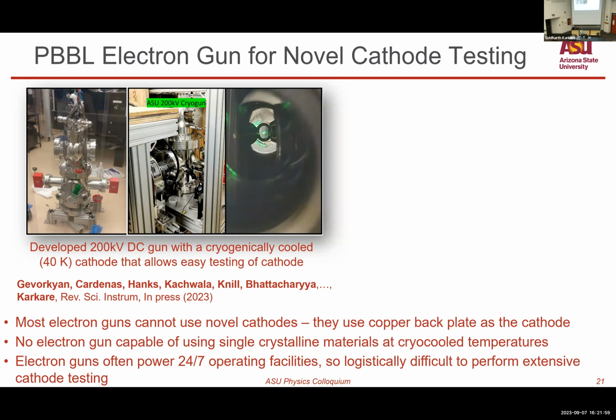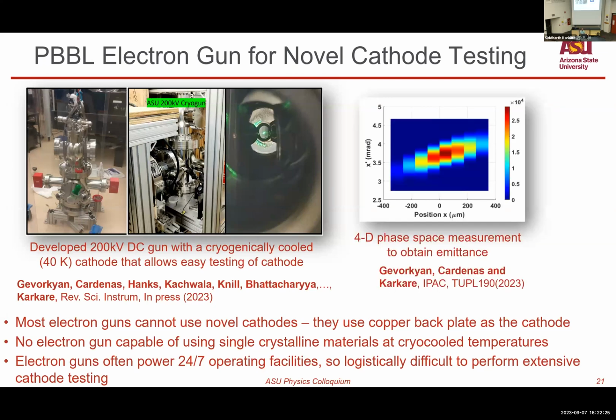But we have successfully demonstrated that, and this is a first of its kind gun where we can also replace the cathode quite easily in UHV, and you have a wide flexibility in terms of the materials we can use as cathodes. You can see this cathode here. This is an alkali antimonide film grown on a molybdenum substrate, and we are using green light to get electron beams out of it. We also commissioned an electron beam line where we can measure the 4-dimensional phase space, so the 4-dimensional emittance, to characterize the brightness of these cathodes. And this is one of the first 4D phase space scans that we measured.